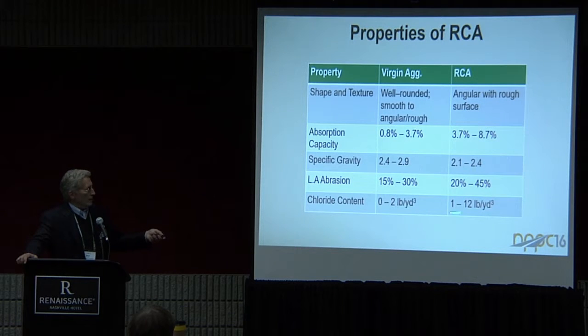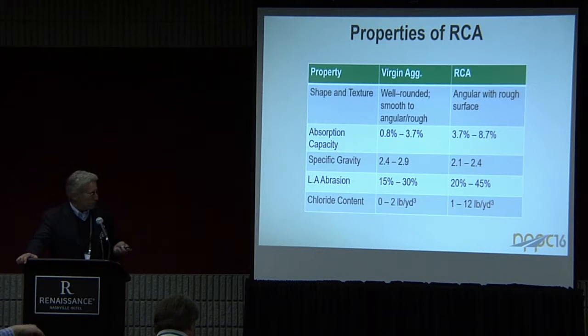And the chloride content can be any number of values here, depending upon where you're getting the material from and whether you're looking at coarse materials or fine materials. If you're from a northern state and you're looking at something that contains a lot of fines, particularly from near the surface, where the chlorides have been absorbed over the years from the de-icing chemical application, you may see some pretty substantial chloride numbers there. If you eliminate a lot of the fines, that tends to drop down to much lower numbers.